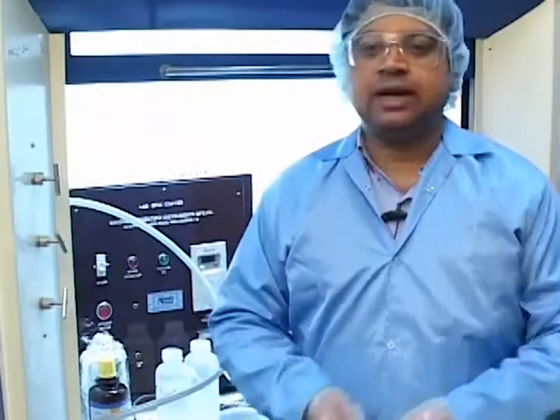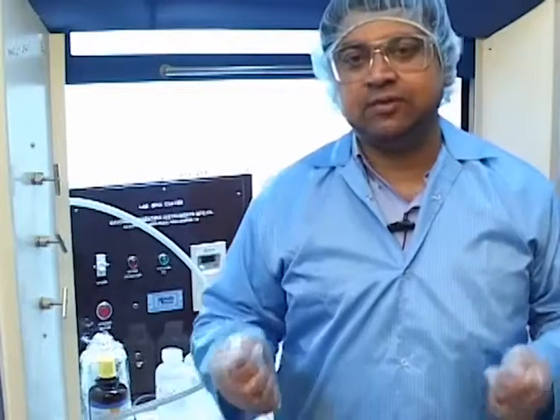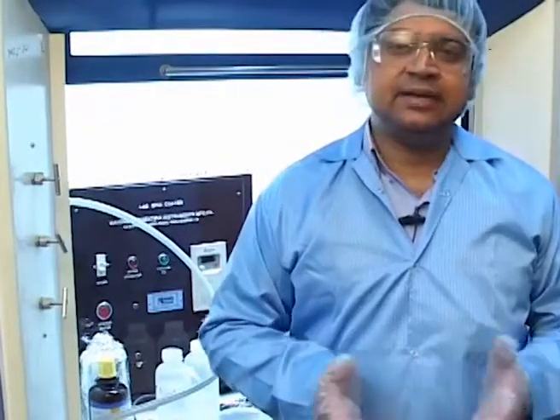And then the idea is to extract the wafer back and rinse it using DI water a few times so that you can remove the acidic impurities, and then dehydrate it in an oven set at 95 to 100 degrees Celsius. So let us look at that process now.